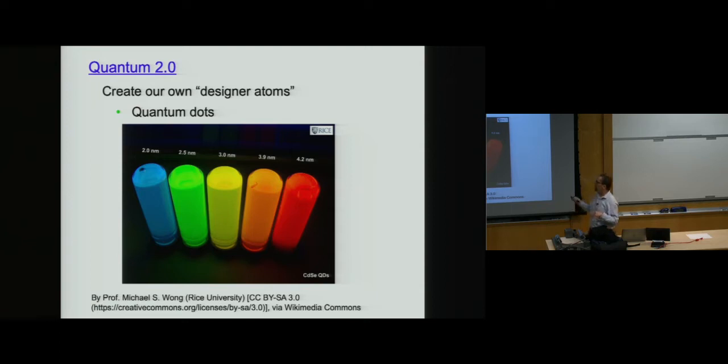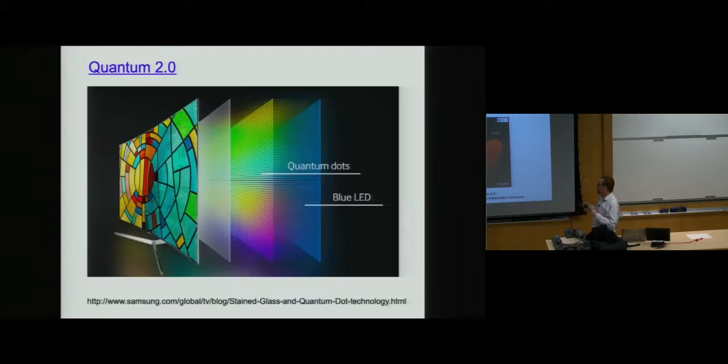So for example, this shows quantum dots, right? You can see fluorescence here at a lot of different colors. But this is all the same material. The only thing I've done is change the size. So these are these nanoscopic three-dimensional quantum dots. And if I control the size on the nanometer scale, I can control the wavelength that they emit. And this is really important because this is all the same material. Cadmium selenide, it's semiconducting material, all the same material, so all the processing that's involved in doing it is all the same, right? So you can kind of manufacture these things much more easily.